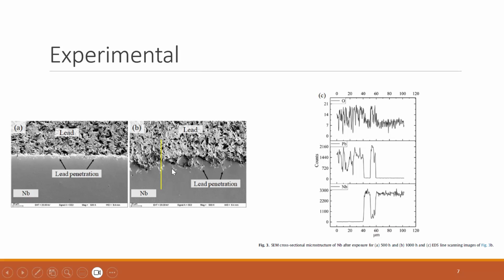So we can see the difference about lead penetration. After 1,000 hours the lead penetration is deeper, more inside. And this is the EDS line scanning image. So we can see this for oxygen, this for lead, and this for niobium.